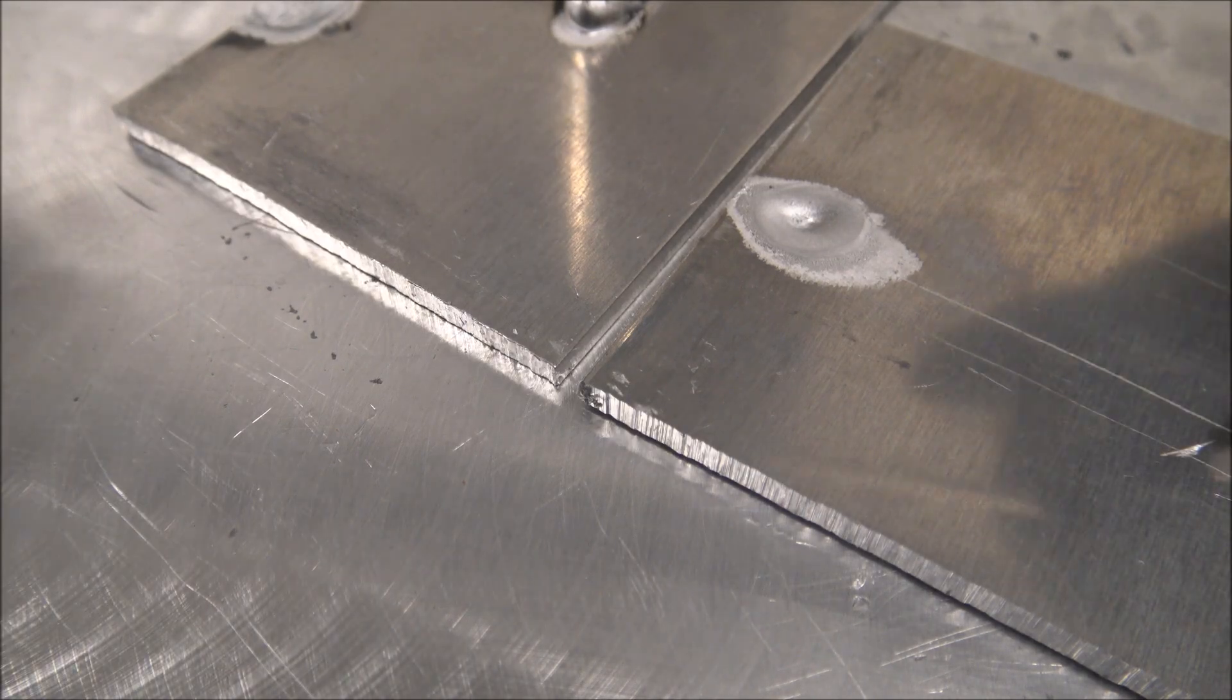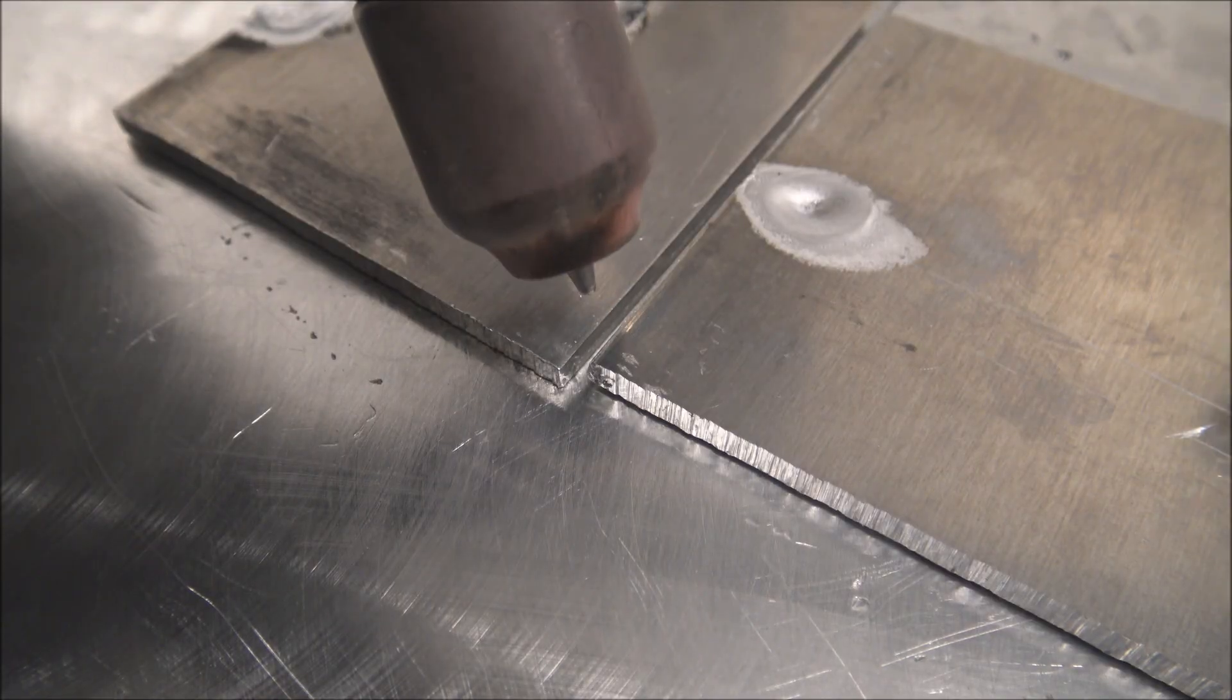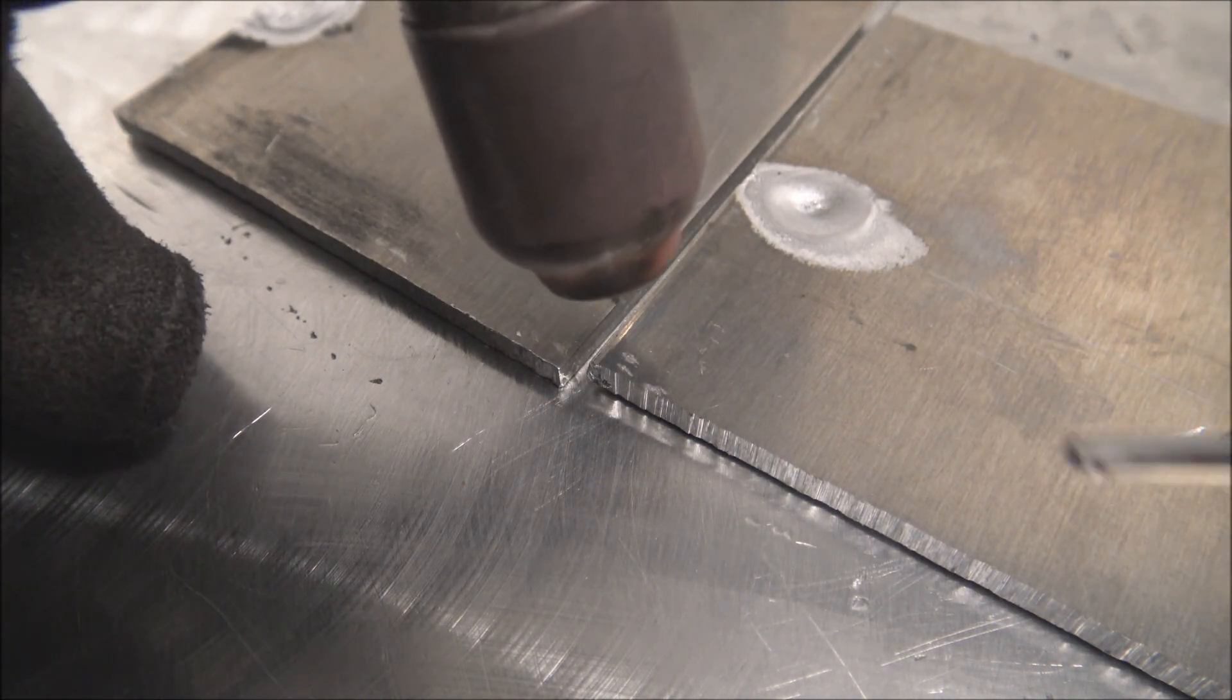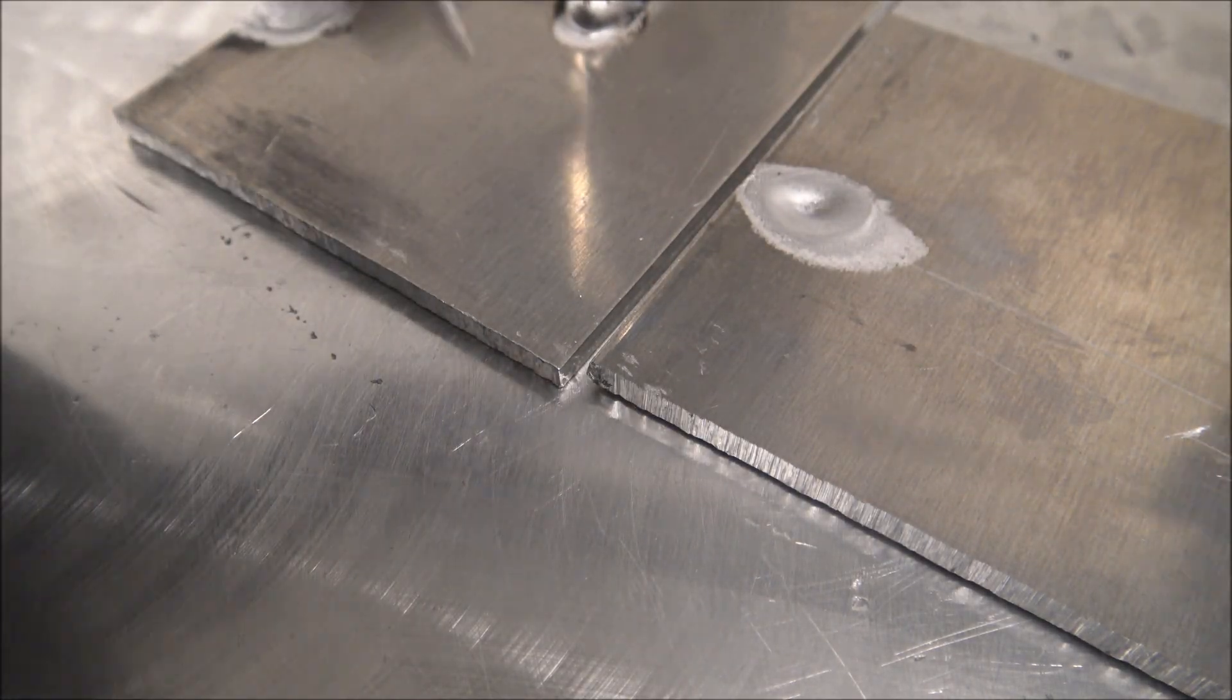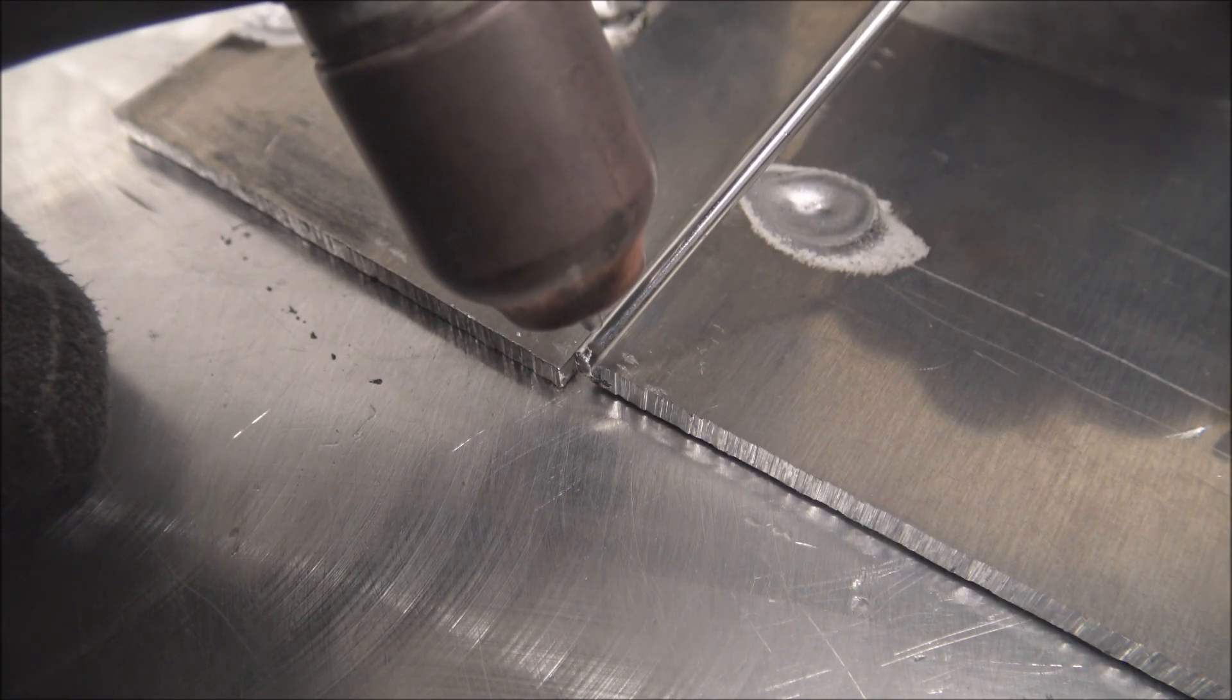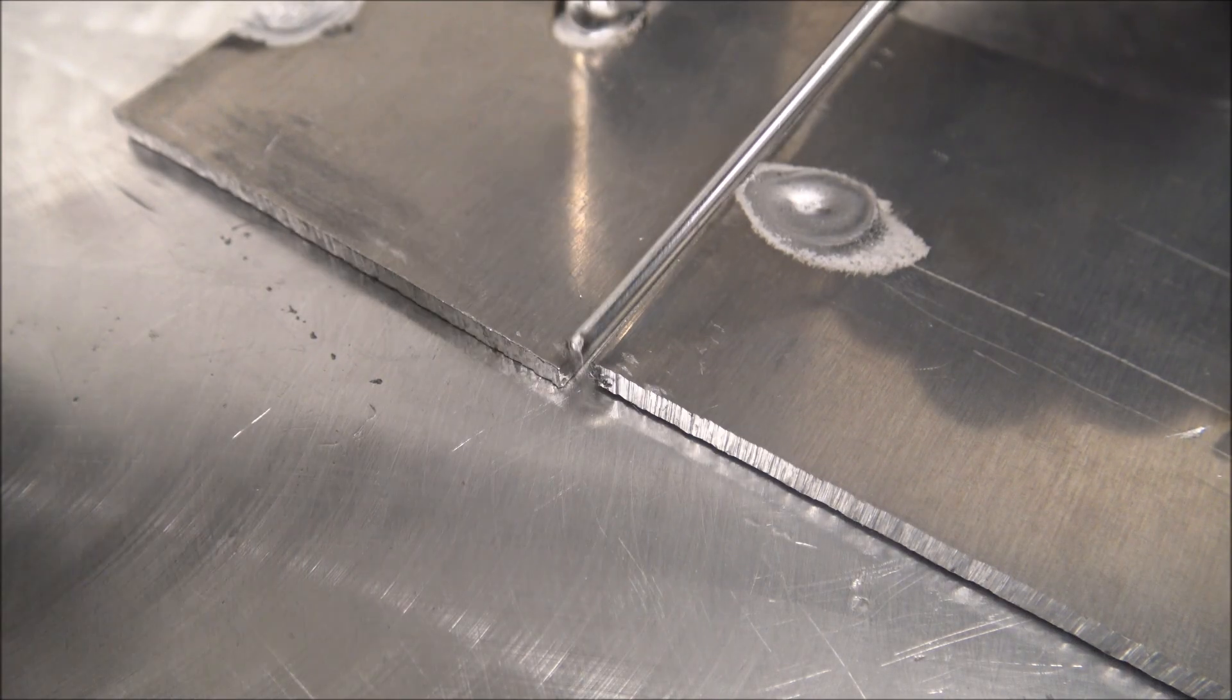Let's talk more about tack welds with filler rod. If you have a gap like this, like I told you, they're not going to fuse together without rod. There's several options to do this. Once you get proficient at it, it doesn't really matter. But a lot of people have a hard time getting both sides liquefied perfectly and then adding rod. Kind of turns into a shit show for lack of a better term. So what you can do is you can lay your rod in here and light up your arc on the rod and liquefy the rod. Then just wet it into both sides, move back and forth if you need to. That's probably the easiest way for a beginner to get this all sorted out.